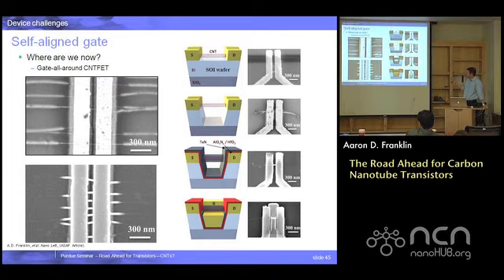And you can see these SEMs show it really well, where the nanotube is sitting on the SiO2, it is charging, so it's glowing, and then it lifts up, goes across the channel, and goes back down. So they're nicely suspended across the middle area, and this is following an ALD, which in our case, we use this adhesion layer, which is a modification of a layer that was used actually by IBM colleagues that are now here when they did the first gate-all-around device, and they used this sort of NO2 functional layer. We modified this to keep it from degrading the transport properties and from contributing to traps and other issues in the dielectric stack. And you can see how the nanotubes coat nicely when they're lifted up off the substrate in this gate-all-around fashion.